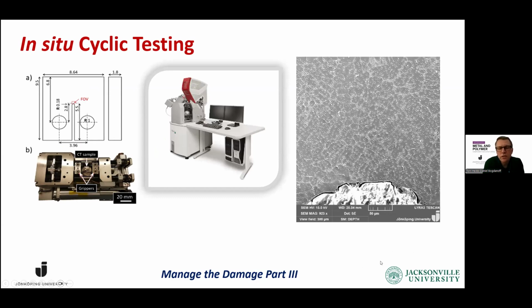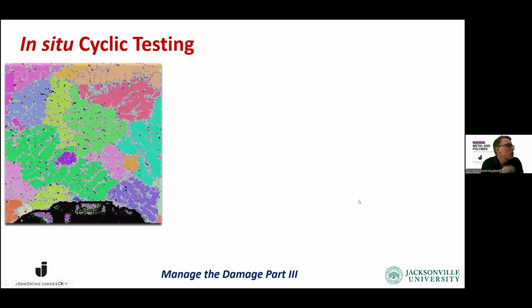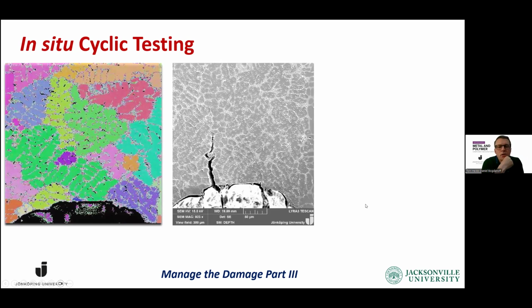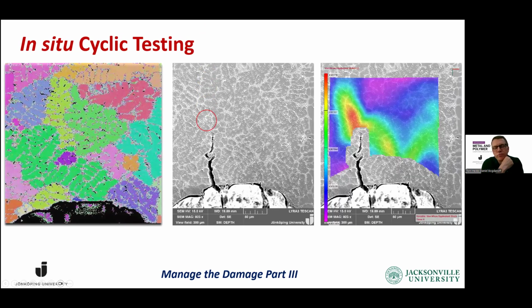So here we actually see what we see in the SEM. We look at a view of 300 times 300 micron when we do the test. And we can get the data out in terms of the grain size using EBSD. And we can also see when the crack is propagating during the test. And here we can see some interesting features in front, applying digital image correlation that Jakob was presenting before.